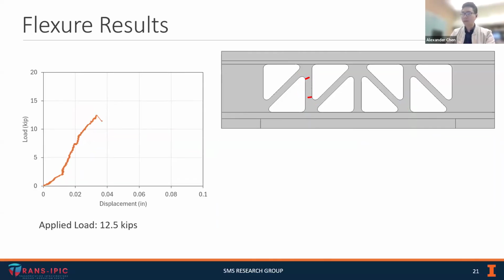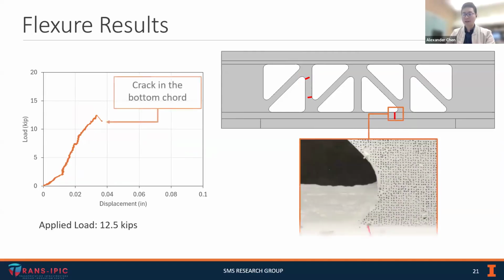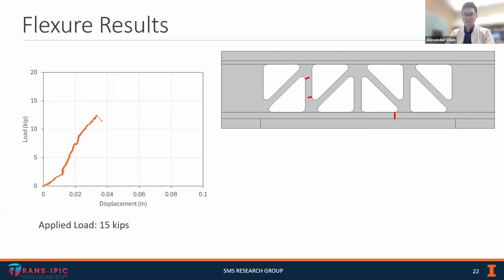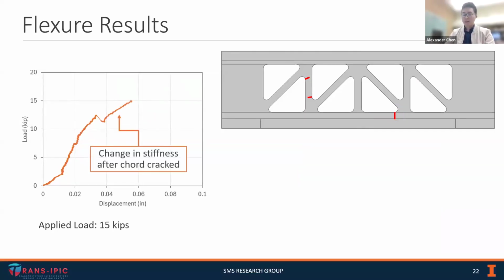We then continued loading, and when we reached around 12.5 kips, you'll see there's a sharp decline in stiffness, and that was because the bottom chord had cracked at this location. And we continue loading after this point. You'll notice that the stiffness is a bit different now that the bottom chord has cracked.